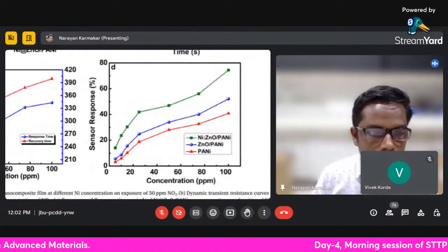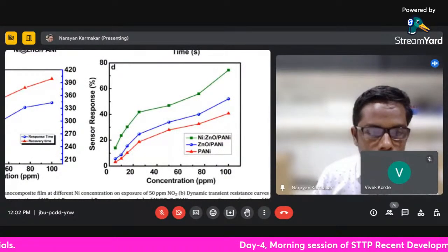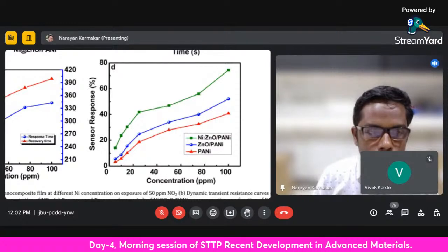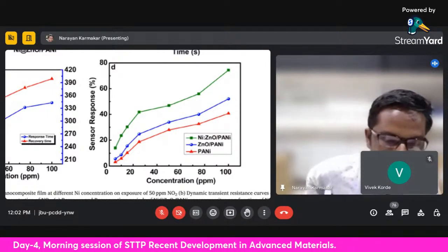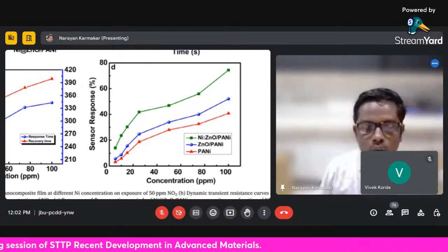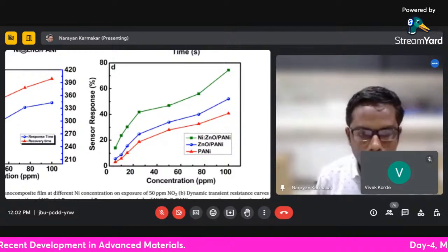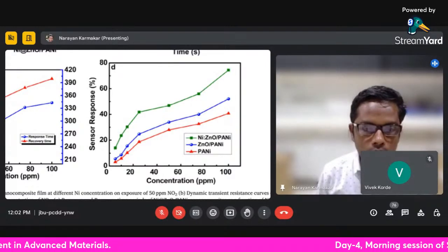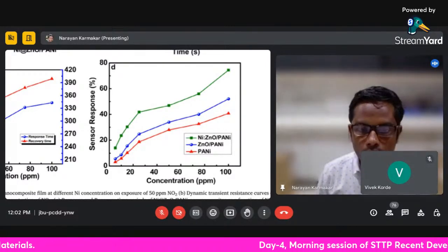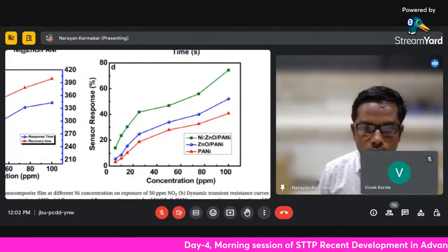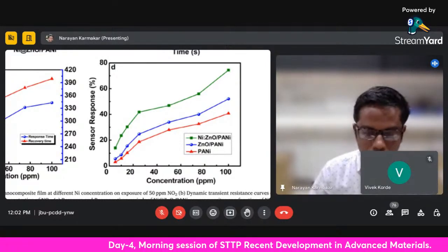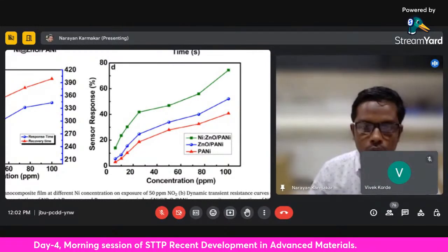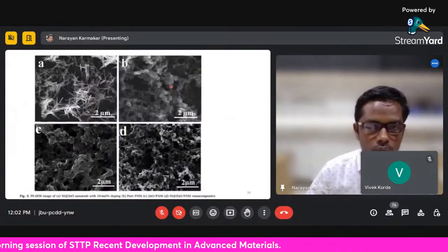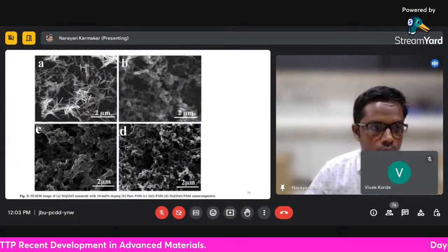Look at this: this is the sensor response in the presence of PANI, zinc oxide PANI, and nickel ZnO-PANI composite. Overall, when you design a material and make sure it is doped properly in the presence of an acid, the overall response increases. This was again confirmed by the SEM images shown here.